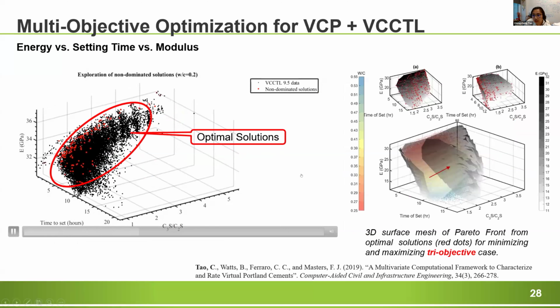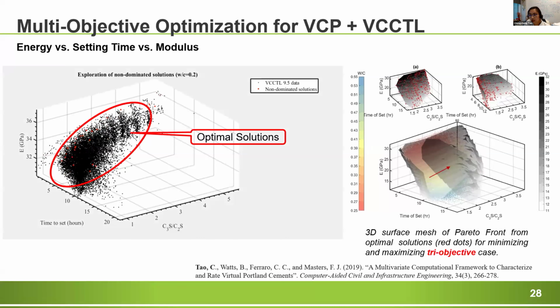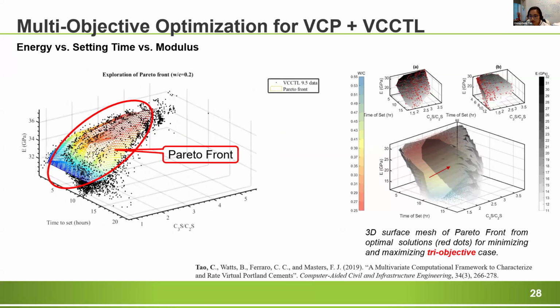So here is another case. Here we want to optimize the 3 objectives. In this case, we want to minimize the setting time, minimize the energy, and maximize the modulus at the same time. So the animation shows how the optimal solution was found by the particle swarm optimization algorithm. And since we have 3 objectives, the Pareto front becomes a 3-dimensional surface, combining all of the optimal solutions. And the right figure shows the 3-dimensional Pareto surface. We are interested in the right Pareto surface because it contains the optimal design for modulus, energy, and setting time for the cement industry.